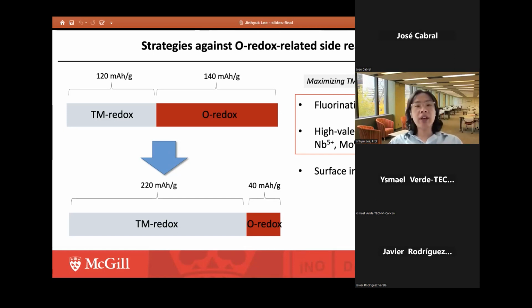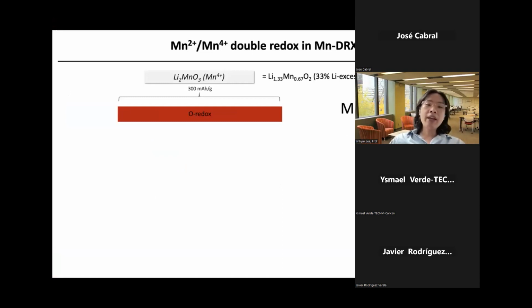So considering this, I'm going to explain the so-called manganese 2+ to manganese 4+ double redox process in the DRX structure to demonstrate how we can maximize the transition metal oxidation capacity in the lithium excess material. Let's imagine we have a lithium excess manganese oxide with the particular composition Li2MnO3. If you renormalize this composition, we can rewrite it as Li1.33Mn0.67O2. So this is essentially a 33% lithium excess material. So it's a highly lithium excess material.